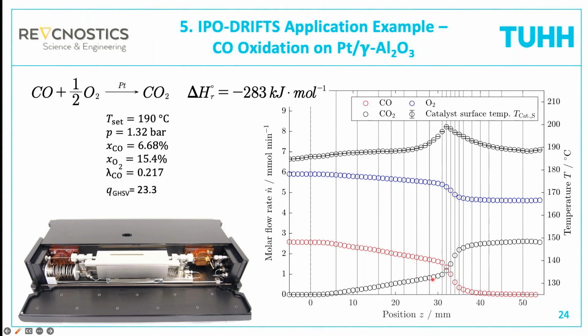Okay, and then because the reaction is so exothermic, you see now how the temperature of the catalyst bed rises slowly. This was measured with a pyrometer fiber, and then comes a point where the reaction picks up speed, and you see now this transition to a first order kinetics, very characteristic. This exponential decay is always for a first order process. And then we get here a hot spot in the reactor, and you see the temperature maximum is basically at the inflection point of the species profile. So everything looks like in the textbook, it's all good.